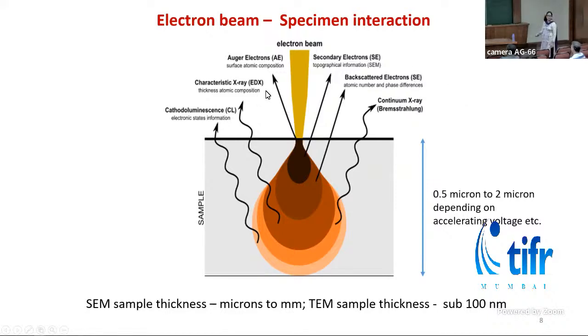Characteristic X-rays, as the name suggests, are unique to the element present in the sample. So we can detect the elements present in the sample if we analyze the energy of this X-ray, and hence we can find the composition. Now, this interaction volume depends on the kV used for accelerating the sample, and it is roughly 0.5 micron to 2 micron in case of SEM. This also depends on the Z number of the sample.